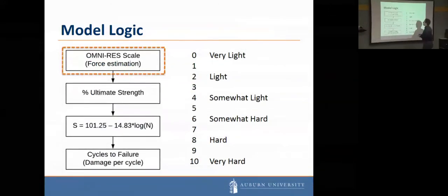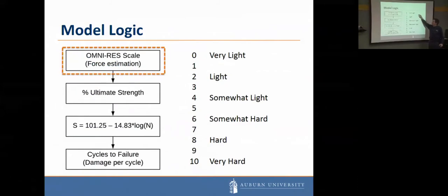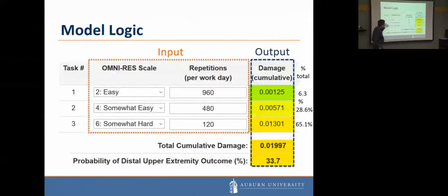So we have a scale. This is actually the OMNI-RES scale. It goes from 0 to 10, where 0 is very light, 10 is very hard, and you have other levels in between. We took those and weighted them, so that when we did repetitions at a very light condition, the multiplier for every repetition is very small. Then it gets larger and larger, exponentially larger, the higher the rating of perceived exertion is. Okay, so we didn't have something like the moment, which is a little more quantitative. This is a little more judgmental, but when we've tested it against epidemiology databases, it also proved out very nicely.